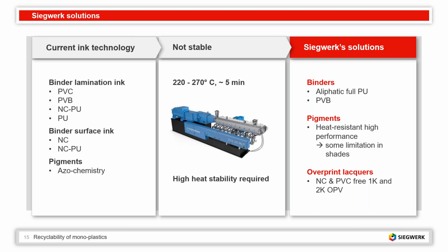The last product group, just to mention it, is the overprint lacquers. They are not pigmented, so they are transparent functional layers, which often in surface printing can be applied to a given printed design to enhance the technical performance. And what we can offer is also systems which avoid temperature sensitive materials, which is nitrocellulose, which would decompose at 250, 270 degrees, and also PVC should be avoided.